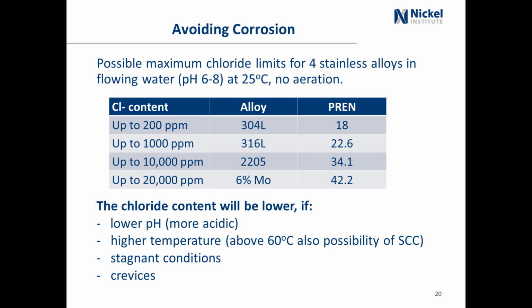If you had an instance where 304L wasn't working, and you knew that the parts per million was, say, under 1,000, well, then, yeah, maybe you look at 316. But if the chloride is more than 1,000, well, then maybe you're looking at something like 2205. These numbers here, they're just rule of thumb guidelines for flowing water at 25 degrees C with no aeration.